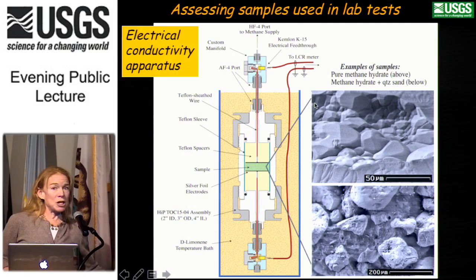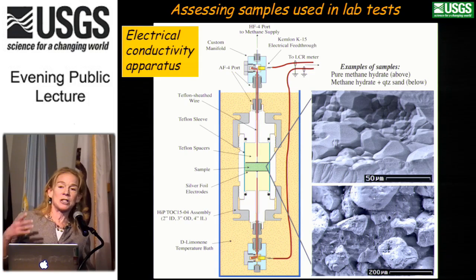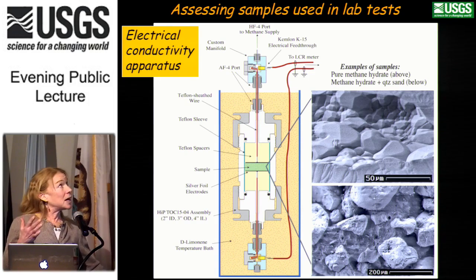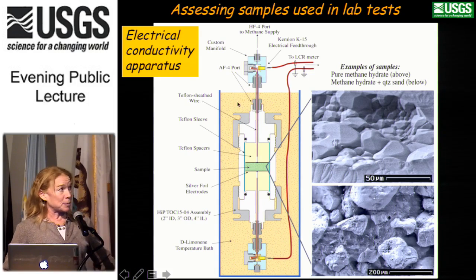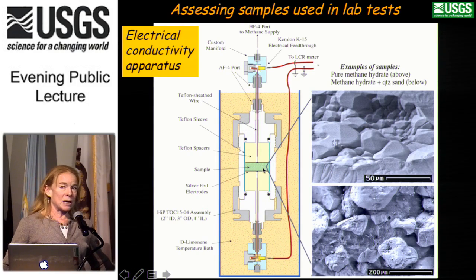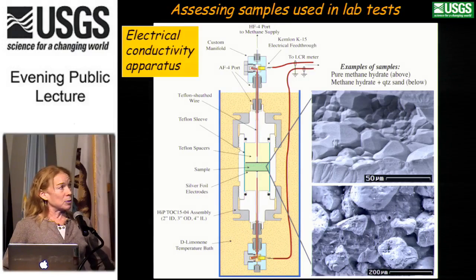So as I mentioned, we use SEM to look at basically all of our samples that we use in physical property tests. Just as one example, we have an electrical conductivity apparatus in our laboratory. I'm not going to go into details, but the schematic of it is shown here. It's a large pressure vessel with, in the very inside of it, we make our sample. And the test may run about a full month or so in duration from start to finish. And afterwards, we'll quench it and remove the sample to look at the final texture.